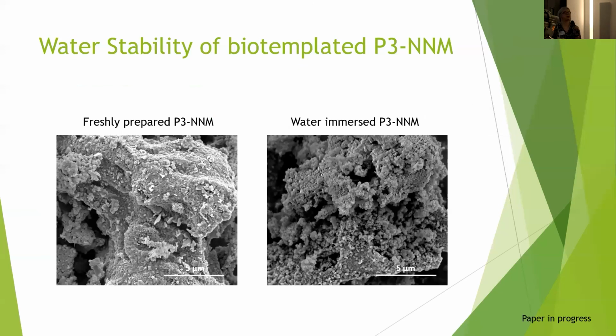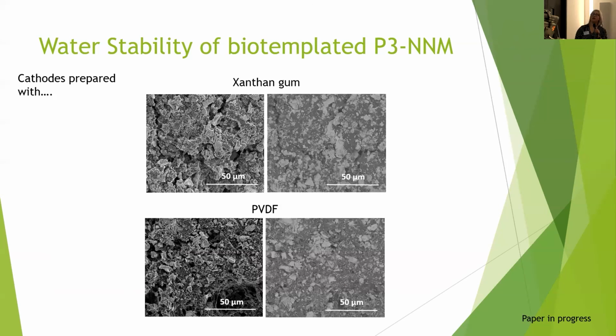I did some SEM imaging just to see if there's actually any difference in the morphology of the material, and I didn't find any significant difference. So you can see that I do have quite small particles, in the range between 100 to 200 nanometers. But after being immersed in water, I couldn't really see anything. And then there are some more SEM images of the prepared cathodes.